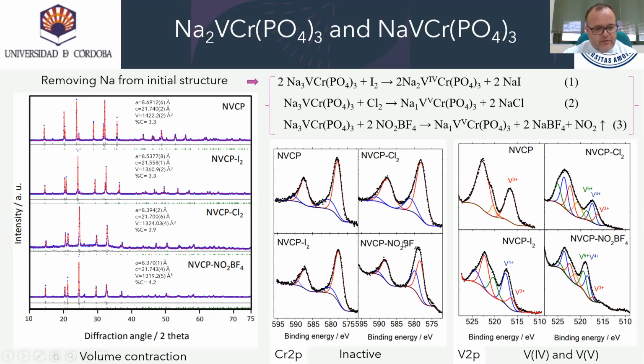XPS spectra of the dissociated sample confirmed that chromium didn't show significant changes in the profile, implying that chromium remained inactive after the chemical oxidation. However, the vanadium spectra show the peaks became broadened and mostly asymmetric when treated with these chemical agents, indicating the appearance of new transitions which would be ascribed to vanadium oxidation to the tetravalent state in blue here, and in the pentavalent state in green. We observe pentavalent vanadium, especially with chlorine and NO2-BF4.